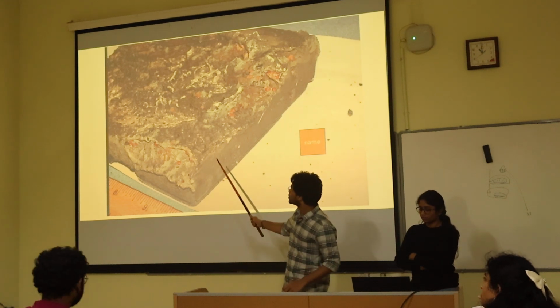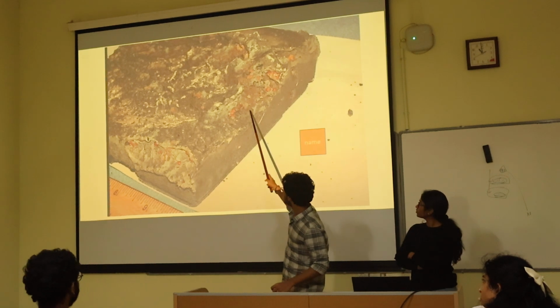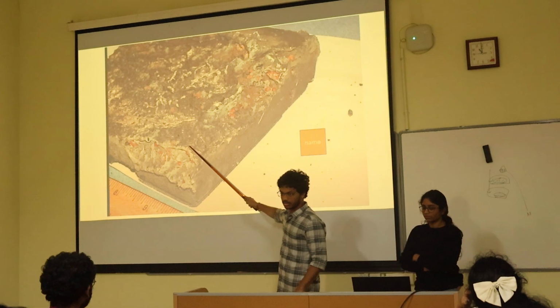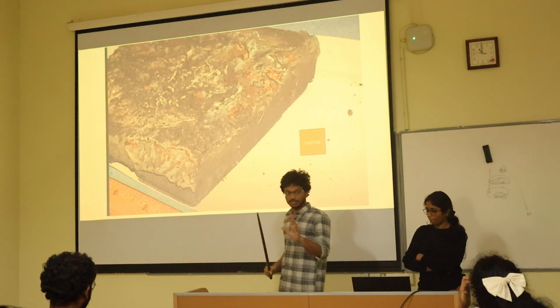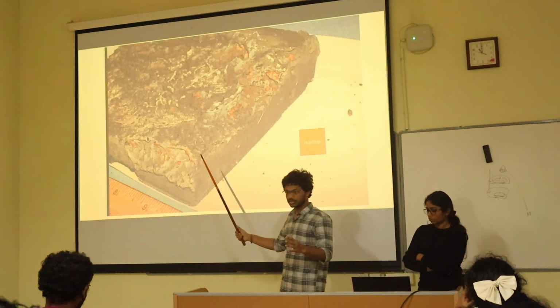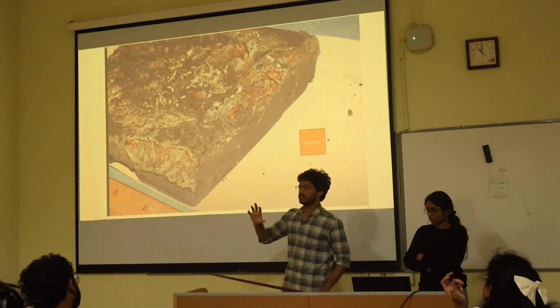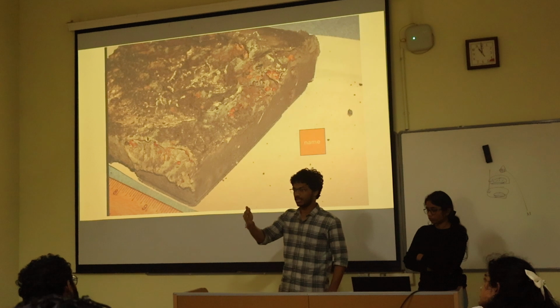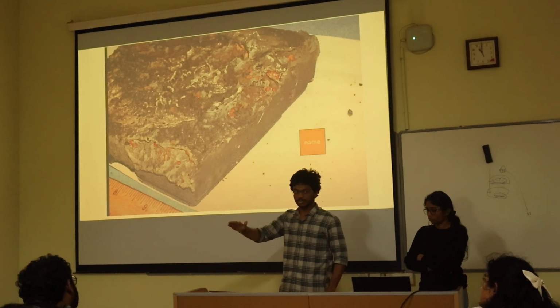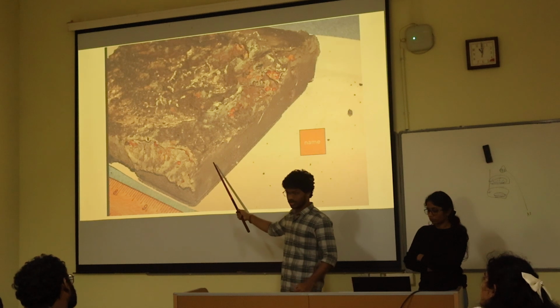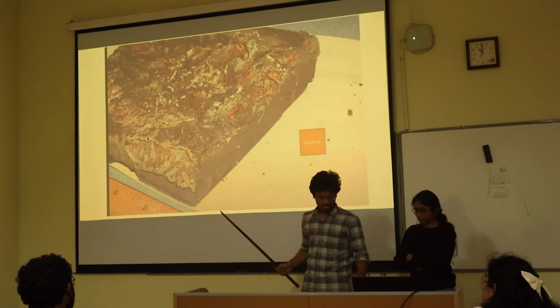What we know from this picture is that there is a metal coating on the ceramic plate. There is no metal outside the shuttle, but there is metal coating in this image. So what we can conclude is that the interior metal part melted and redeposited on the ceramic plate from the left.